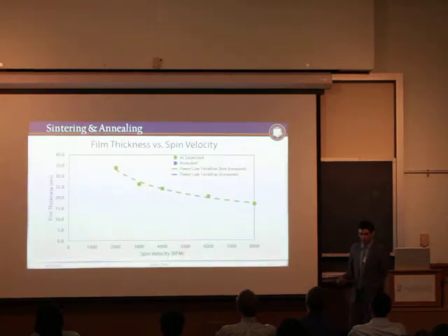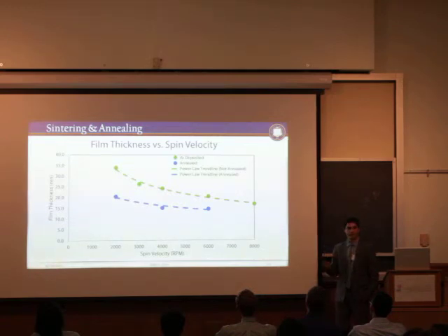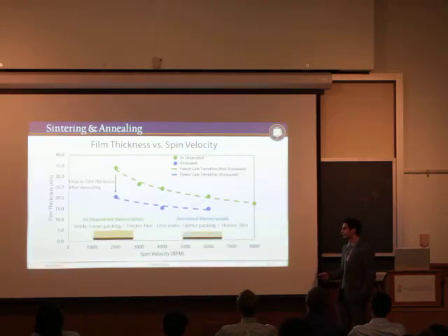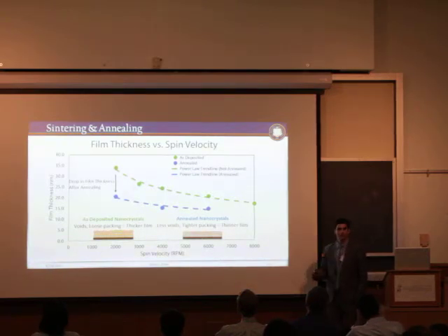And now what we do is we just do another quick atomic force microscopy test, see the thickness of these films after annealing, and what we see is that there's a drop in thickness after annealing. That's really easy to sort of explain. Nanocrystals are loosely packed, you heat them up, they start to coalesce and become packed tighter, so thickness essentially decreases.